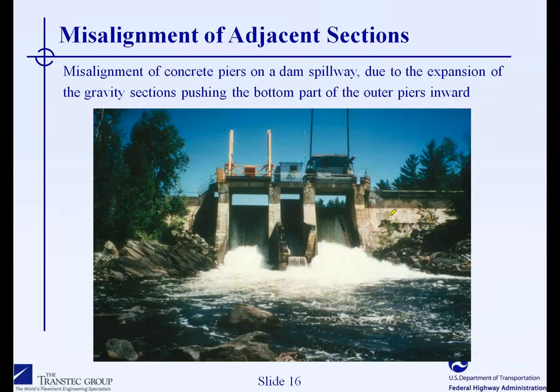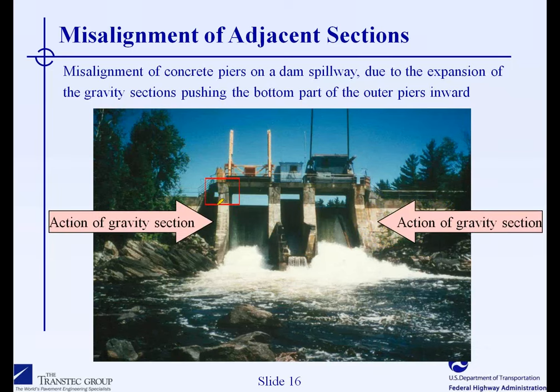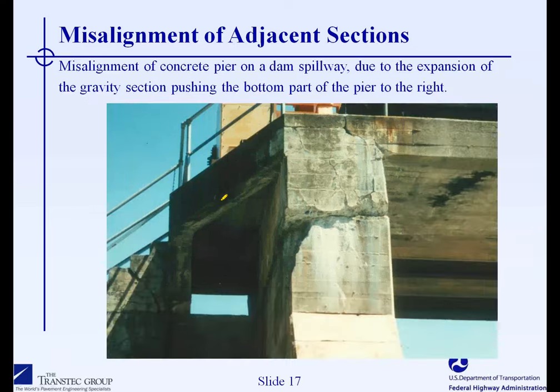This can be seen in this example here. This is a hydraulic dam. There is a lot of AAR expansion happening in the more massive section of the concrete dam, and the expansion is restricted in different directions, but it's easier for the concrete to expand in the directions toward the spillway here, as you can see. This push that you get from expansion due to AAR, you can see the effect here in the upper portion of that concrete pier. If we look at a magnification of that area, the effect of the expansion of the underlying mass section pushing towards the spillway has caused the failure of this pier and also jamming of the gates in the spillway.